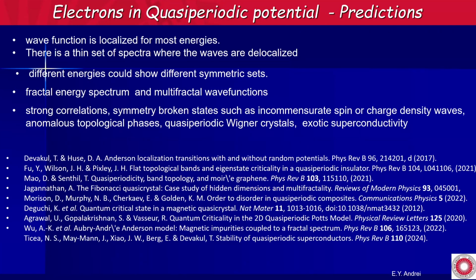So what does theory tell us about the quasi-periodic potential? Most of the wave functions should be localized. There's a thin set of spectra where the waves are delocalized. You get different symmetric states, different symmetries. You have a fractal energy spectrum, multifractal wave functions, strong correlation, topology, quasi-periodicity, a lot of very interesting things that are predicted. And this is just a subset of the paper. And this is all open.